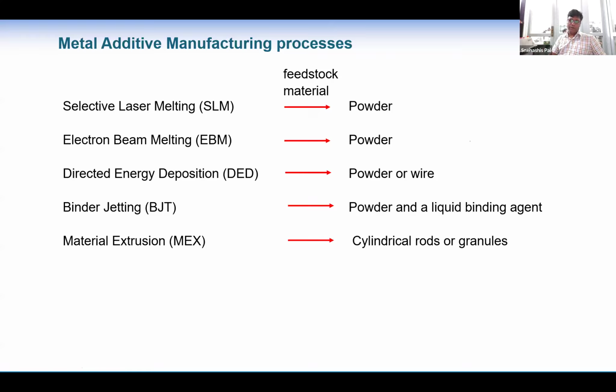Selective laser melting can use not only titanium alloy for permanent bone implants. Sometimes we may need degradable material, for example aluminum, maybe magnesium or zinc, or their alloys, which are good for degradation during bone growth. They will be slowly degraded, so a second surgery is not required. Whatever design we need for controlling the degradation rate, we can fabricate by selective laser melting, and then we apply it. So that's why 3D printing of metal is very popular nowadays for bone implants.